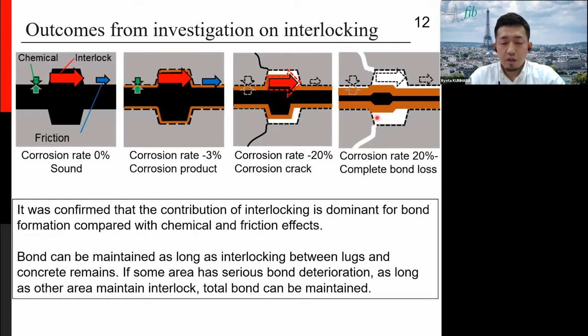But even under this condition, if a sound bond area exists in other parts of the rebar in the axial direction, it can resist the force, and the bond can be kept as a whole of the member and the rebar slip can be prevented. As a whole view, the bond can be maintained as long as the interlocking between lugs and the concrete remains in some area. Even if some area has serious bond deterioration, if the other area keeps interlocking, the total bond can be maintained.